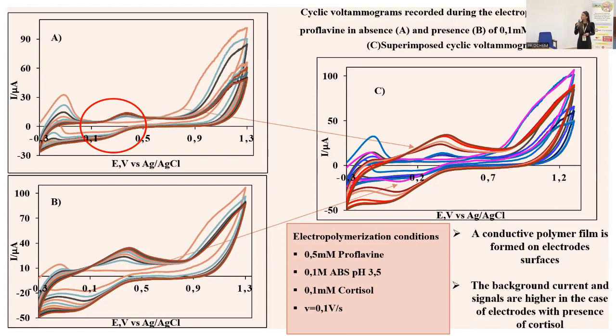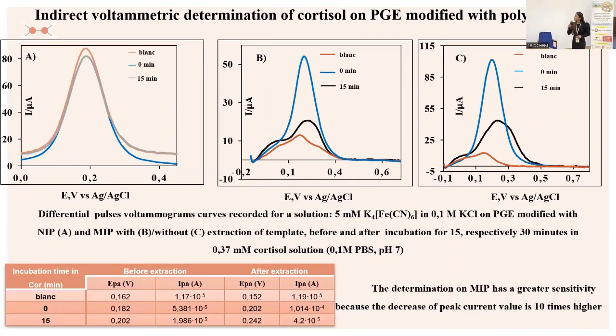And this indicates a change in the structure of the polymer due to the incorporation of cortisol into the polyproflavine matrix. The next step was the indirect determination of cortisol by using these modified electrodes, using ferrocyanide in the presence of cortisol. All measurements were performed in phosphate buffer solution.